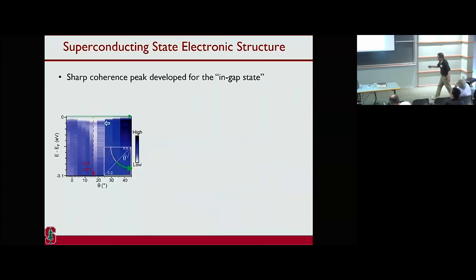Okay, so again, let me show you. I go from here to here, okay, in K-space, with spectra each taken one by one. You see this feature? This band grew to higher energy and shows up with a maximum somewhere here. That's the hotspot. Of course, that's the largest part where the antiferromagnetism happens. But if you look carefully, you also see another one, okay? This one is at much lower energy and also shows up at a maximum, furthest away from the Fermi level, and this one basically shows a peak in this spectrum.